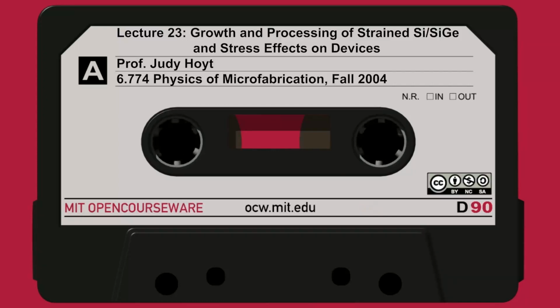Phosphorus doesn't help the situation. Phosphorus is also enhanced, maybe about a factor of 2 or 3, depending upon the temperature. This line here gives you an idea roughly of the diffusivity of germanium. Well, this is at a very low germanium fraction as a function of temperature. It's diffusing slower than the dopants, at least at this germanium fraction.